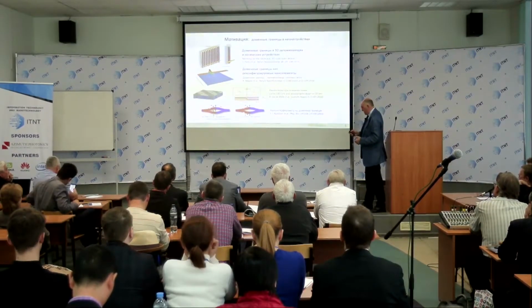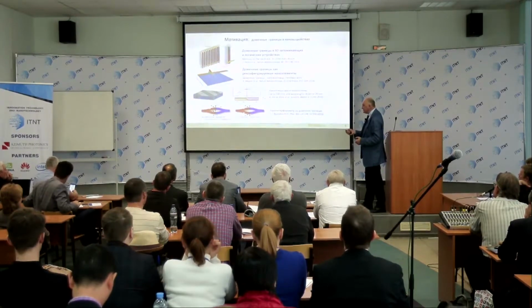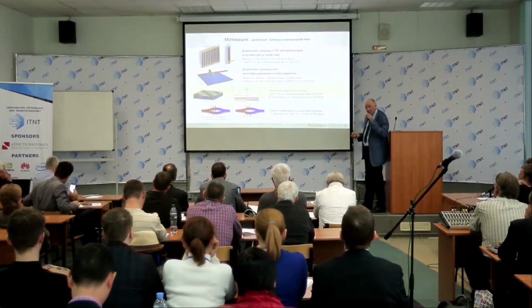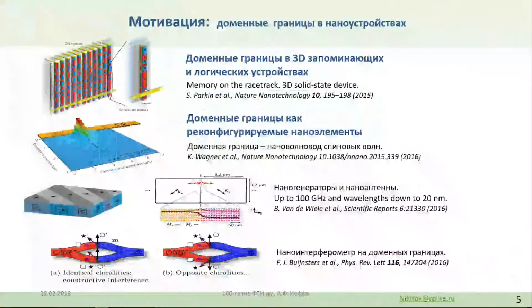Therefore, we can produce a film in which a single domain wall can be moved by the field. And a single domain wall, as I said, can have dimensions of about a few nanometers. And this produces already a waveguide for the waves over quite a long length. The width here is less than 1 micron, but it can be tens of nanometers, while the length in this direction can be a few microns. Therefore, it's a very long waveguide with very narrow width.